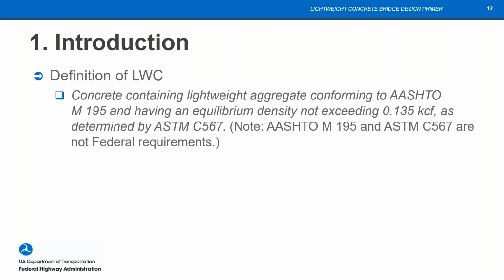What goes on here is that lightweight concrete is pre-wetted, the aggregate rather, is pre-wetted before it's batched. Therefore, it has some extra moisture in it, and that moisture can get away. Well, that moisture weighs something. So as that moisture leaves the concrete, if it's not bound in the cement, then you're going to get a reduction in the density of the concrete. So that's why we are talking about an equilibrium density.